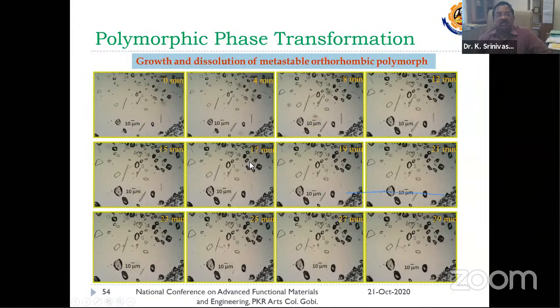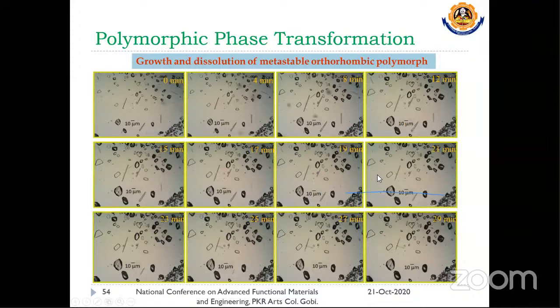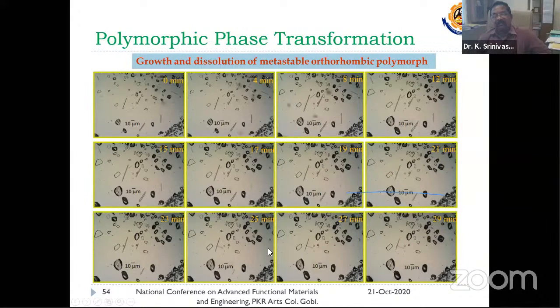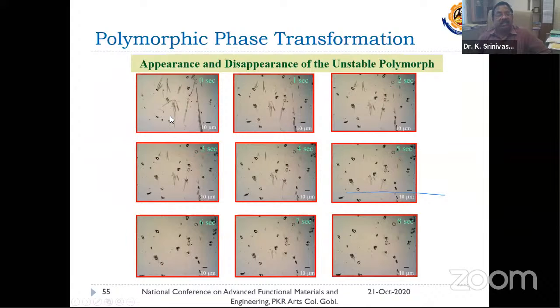these monoclinic crystals continuously grow in size, whereas these orthorhombic needles become blunt and thinner. After a period of about 30 minutes, the orthorhombic form completely dissolved into the solution, and only the stable monoclinic form remains. So that kind of stability, here only 30 minutes. In some other process, when you redo this experiment with different experimental conditions, this will last for 1 hour, 2 hours, or sometimes 1 day, etc. And this is the appearance and disappearance of the unstable polymorph we encountered.